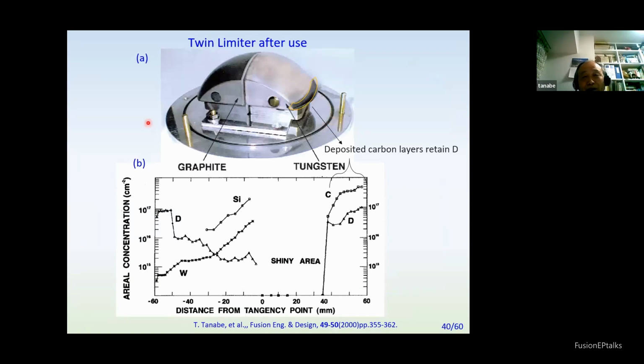This deposition also clearly appears because tungsten has a high reflection coefficient, so deposition is quite small. While in carbon, very large deposition appears, and in carbon, deuterium is included very much. That means carbon traps deuterium this way. So this is a clear indication of how different materials behave in the plasma.